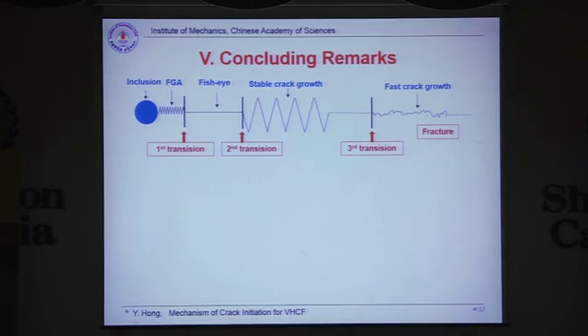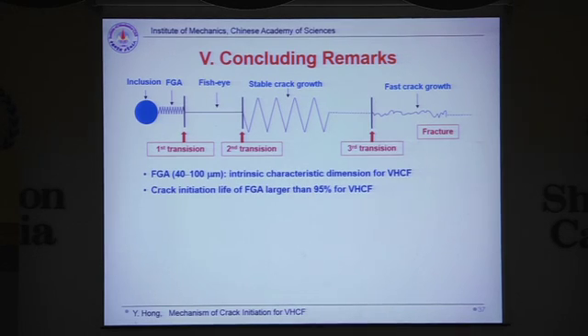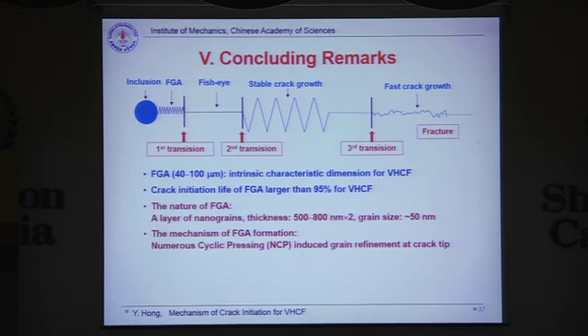And now I conclude my talk. The first is that the region of FGA is very interesting and important, and the size is between 40 and 100 microns. It is an intrinsic characteristic dimension for very high cycle fatigue. And the crack initiation life is larger than 95% for very high cycle fatigue. And the nature of FGA is a layer of nanograins, about 500 to 800 nanometers thick on both surfaces, and the grain size is about 50 nanometers. And the mechanism of FGA formation is due to the numerous cyclic pressing induced grain refinement at the crack tip.